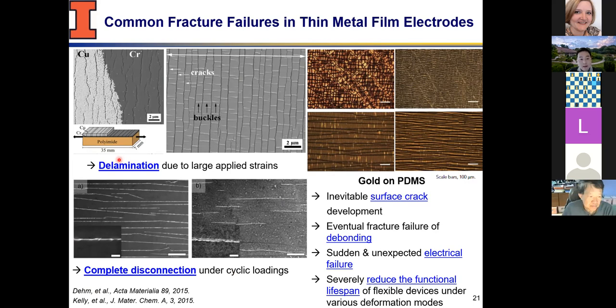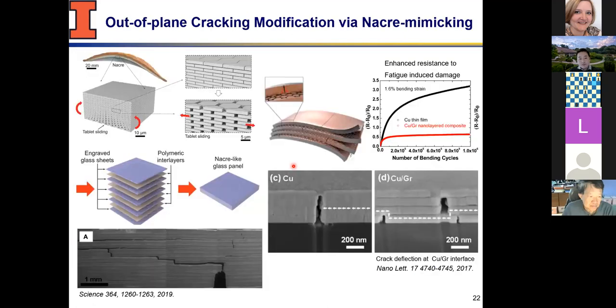So if you have a polymer elastomer or a polyimide or any flexible substrate that people use for flexible electronics, once it reaches above the fracture strain, the typical fracture surface that we see is a very straight crack. When you, let's say, pull it this way, that's what you see, mode one type of fractures of metals. Copper and different metals have been shown to have similar behaviors. They may have slightly different strain dependent fractures, but they nonetheless show these very straight fractures in these cases.